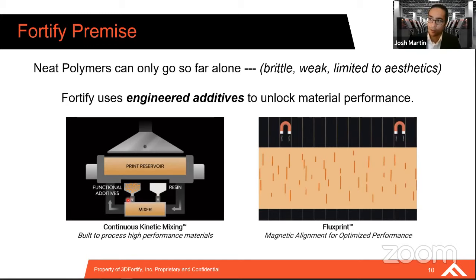And in addition to continuous kinetic mixing, we're also leveraging essentially what my PhD work was focused on, called Flux Print. It's using magnetic alignment to control fiber architecture. Anyone with a background in composites will appreciate this idea that fiber alignment is key to really getting the most out of your performance. In a traditional composite, if you load the material along the fibers, it'll actually be several times stronger than if you were to load it in a transverse direction. And so this ability to order our alignment really goes a long way.